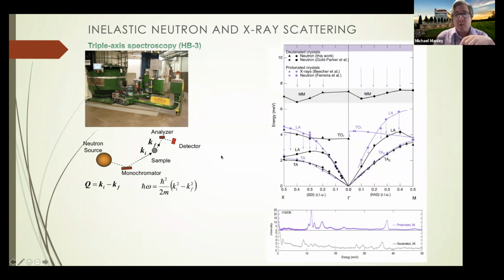Okay, so on the right here, I'm giving you a summary of the dispersion curves. So there's a couple of things here. First thing is that there's two different colors here. The black is the deuterated, and the purple is the protonated. Now, the first thing that happens is that, and we did an additional measurement down here for the high energies on the time of flight instrument.